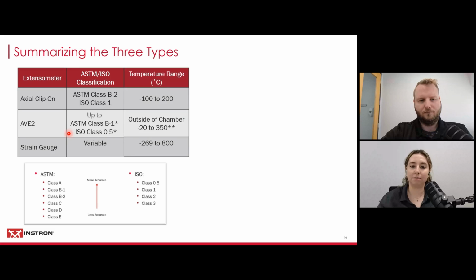And then your bonded strain gauges, that's going to be variable and is going to come from the manufacturer of those bonded strain gauges. In terms of temperature range, that clip-on, as I said before, is capable of going inside of a chamber and can handle -100 to 200 degrees Celsius. The AVE2 is capable of viewing through the window on the outside of the chamber and can handle from -20 degrees to 350 degrees Celsius. I have a couple more asterisks because if we get any lower than negative 20 degrees Celsius, we risk actually frosting over the glass on our chamber, which can cause visibility issues with the AVE2. So you have to be cognizant of that. And then the strain gauges have the highest temperature range of negative 269 to 800 degrees Celsius.